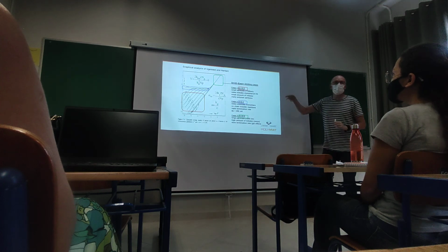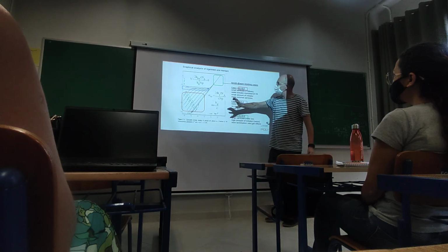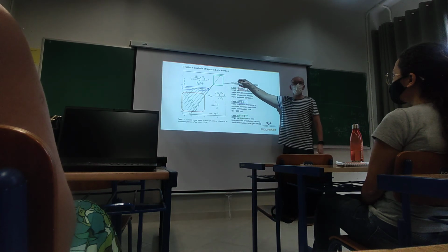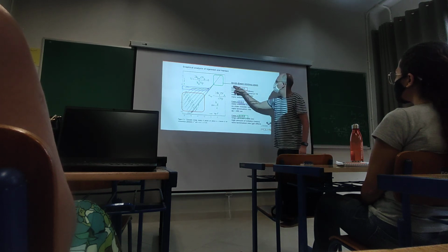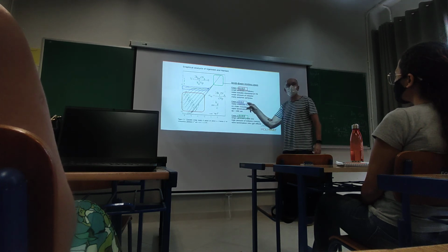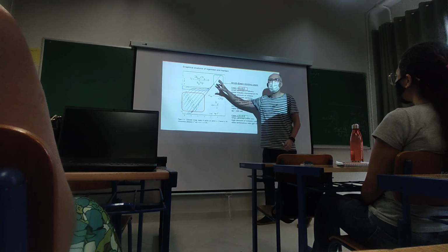Okay, and to finish this part, in which experimental conditions are we in the different regions. By the way, I didn't say that these three regions were the regions that in 1948 Smith and Ewart identified qualitatively. Okay? So they defined Smith-Ewart case 1 as where n bar is below 0.5, Smith-Ewart case 2 is n bar equal to 0.5, and Smith-Ewart case 3 is n bar higher than 0.5. Ugelstad and Hansen were able to do this with quantitative equations.